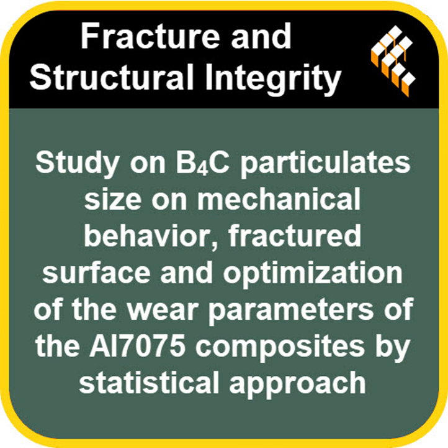The material sort of creates its own protective layer and smooths itself out as it wears. That is remarkable. Material that gets tougher the longer it runs, in a way. Okay, what about the coefficient of friction, the COF? Basically, how sticky or resistant the surfaces are to sliding against each other. Right, friction. Here, the COF decreased as the particle size was reduced. So nano had lower friction. Why lower friction with nano?